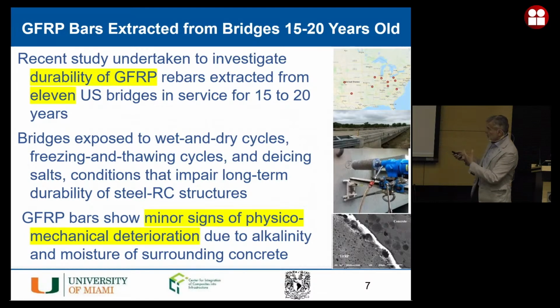So in this project that actually was sponsored by ACI itself, we collected samples from bridges that had been in service already for 15 to 20 years. Here you see the various locations. All of them but one, I was involved in their design, by the way, so it's something that I knew. And then we selected samples, we brought them to the lab, we tested, and we saw that the signs of physical chemical deterioration were minor. So we know for sure that if we design with these materials that follow the ASTM D7957 specs, we can assure a service life of the structure of 100 to 120 years. So this is a significant jump from what we do with conventional structures today.